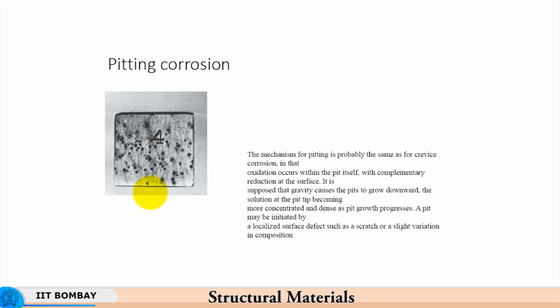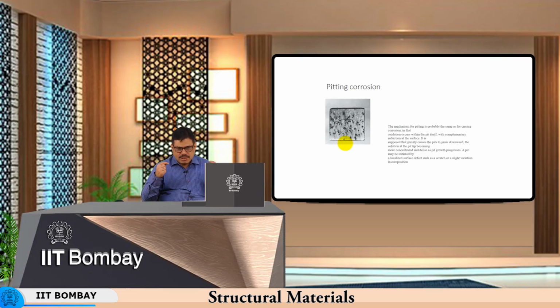and as the solution becomes more and more concentrated and the pit growth progresses, the rate of corrosion will also be that much higher, because now the corrosive attack, the current density, is going to be much higher as the pit gets deeper and deeper. So, the cause could just be a surface flaw, a machining mark, a defect such as a scratch or a slight variation in chemical composition. As I said, if you have two different phases present, one is more anodic with respect to the other, then that phase will get eaten away first. Now, if the phase gets completely removed, then the corrosion will automatically stop, but if the phase does not get completely removed, it has its presence throughout the thickness, naturally you will find the corrosion progressing right through the thickness.